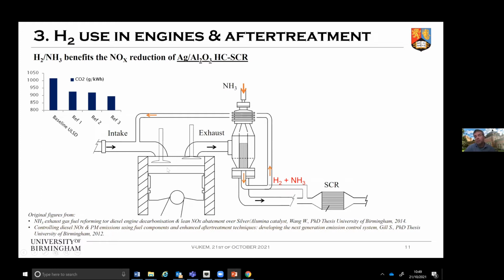Then we were able to replace some of the diesel fuel. This brought some advantages in terms of CO2 emissions. Depending on the composition of this mixture of hydrogen and ammonia, we observed that with a higher proportion of hydrogen, the mixture burns better, and we are able to obtain further reduction in CO2. But also what we did is take this hydrogen and ammonia mixture pre the SCR and try to see how effective it would be for our SCR catalyst.